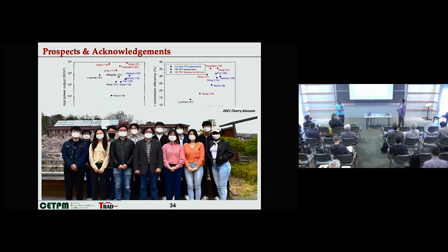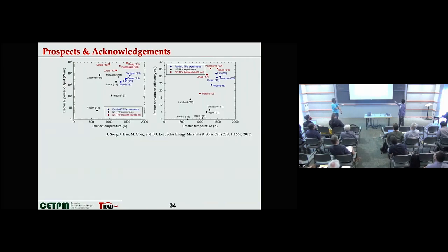Yeah, you're right. Everything that I present here is first law, and the best for the near field. I think the French group achieved about 14%. Ours, we cannot see; I have to plot in log scale because we use the Schottky junction, and it has very low efficiencies. The far field can reach about 35 or even close to 40% first-law efficiency, so there is still more than a double gap. More questions?